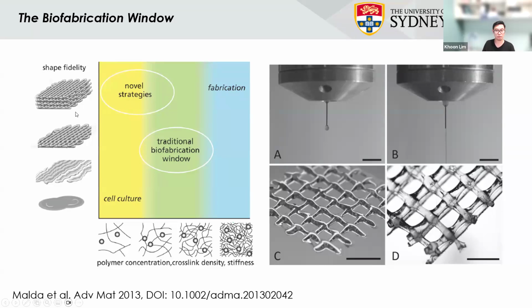But unfortunately, if you want a polymer or a bioink to print really well and get really good shape, you often have really high stiffness. And if you think about cell culture, if you have very high stiffness, you are restricting the cells from migrating, elongating, or forming interconnected networks within them. So if you want cells to be happy in these bioinks, in these hydrogels, you want them to be permissive. So you want less crosslink density and less polymer concentration, so you can have all of the oxygen and nutrient diffusion and metabolic waste removal, and also give the cells space so that they can spread and elongate.